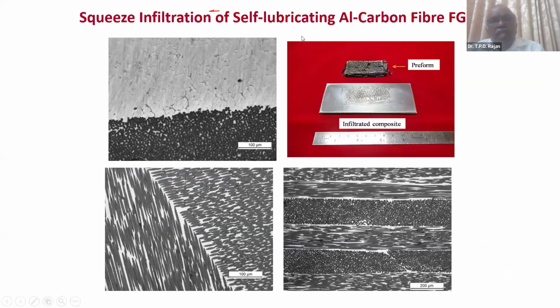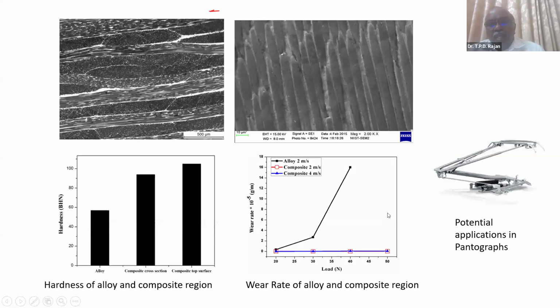And we had also used carbon fibers to make composites. When the carbon fibers are stacked and infiltrated, we can see these are stackings of carbon fibers in different directions. So these are the longitudinal directions, and this the horizontal or the diameter directions, and we can see it's completely infiltrated. And this particular composite has very good self-lubricating properties, because you have these carbon fibers. Because of self-lubrication, you can see this is a pure alloy. It wears off very easily. The wear rate is very high. But with the composite, the wear rate is very less.